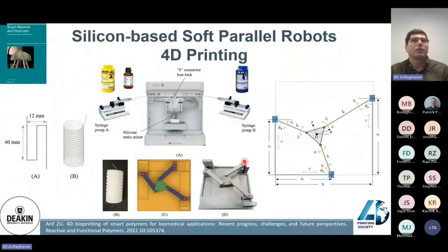And we were able to develop the silicone, which you will see in the later slides, using 3D printing. It is not quite a straightforward application, but using Ecoflex and Silicone A and B, we could achieve some sort of 3D printing of silicone, and with adding ethanol, based on some of the earlier work of other colleagues in soft robotics, we could develop these parallel robots.